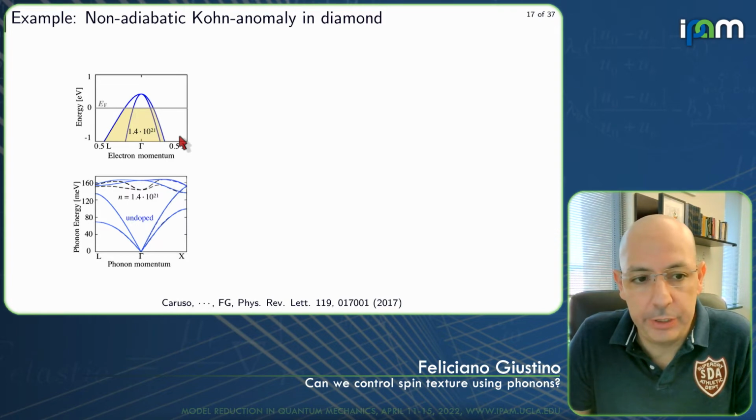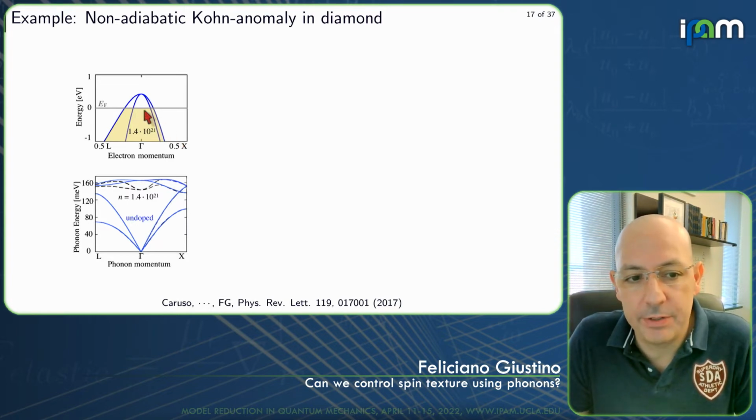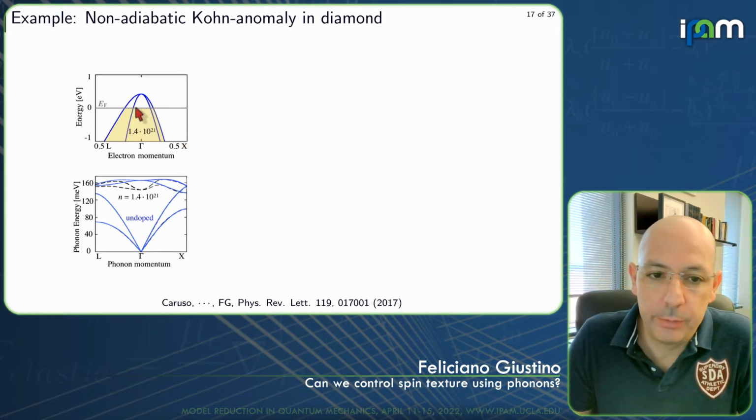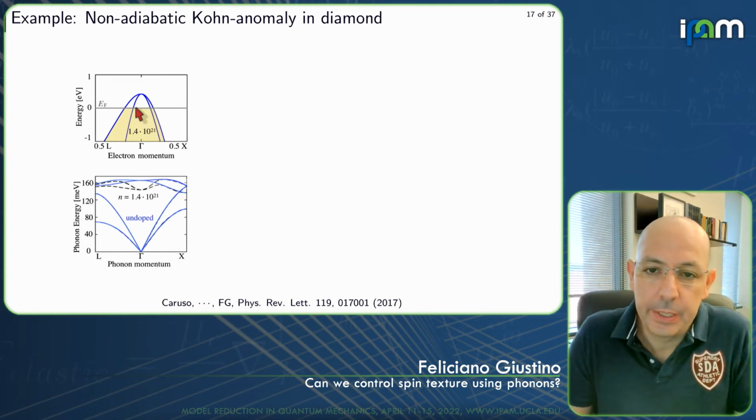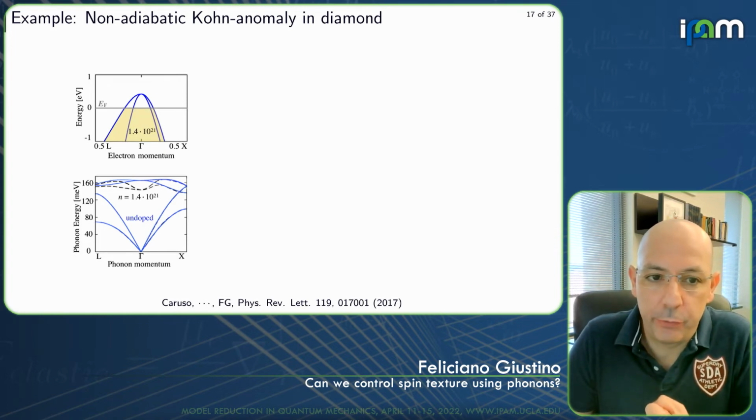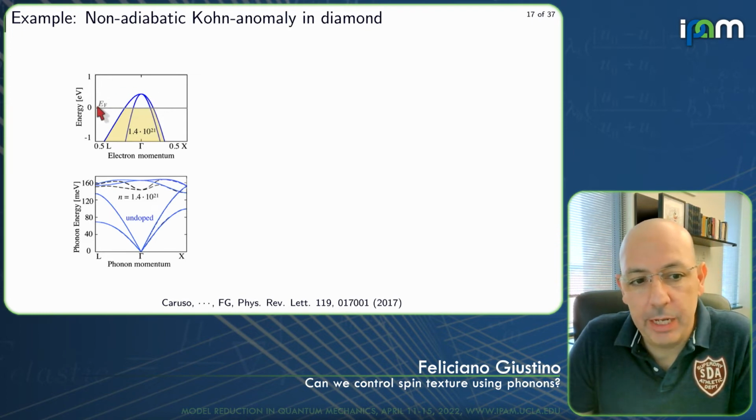Diamond is a perfect insulator, but if you replace some of the carbon atoms by boron, since boron has 3 electrons instead of 4, you reduce the number of electrons. So you are performing hole doping of this compound, which means that the Fermi level is moving down from the valence band top.